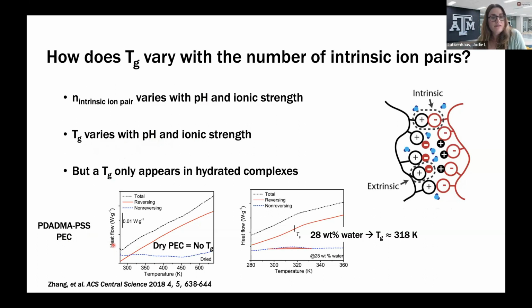So here is a modulated DSC thermogram of a dry PDADMA PSS complex. We have to do modulated DSC because the glass transition is very weak, and this method is very good for amplifying the signal. If you were going to see a glass transition, it would show up in this red non-reversing curve, which contains all the heat capacity information. But you see nothing. So dry polyelectrolyte complex, no glass transition. When you handle it, it's really brittle.